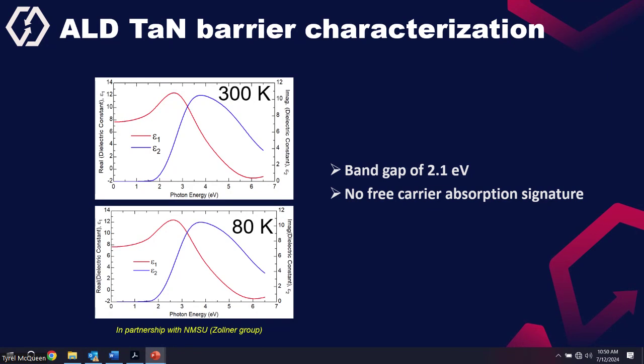And from the modeling, the band gap came out to be 2.1 eV, and there was no free carrier absorption. So from this, we determined that we can use it as a tunnel barrier, and its band gap is lower compared to the aluminum oxide, which is usually used as a tunnel barrier in aluminum-based junctions. If it is lower, we can use thicker barriers for our Josephson junctions, which is another advantage, because when aluminum oxide is about 1 nanometer or something, it is very difficult to control the thickness and stuff.